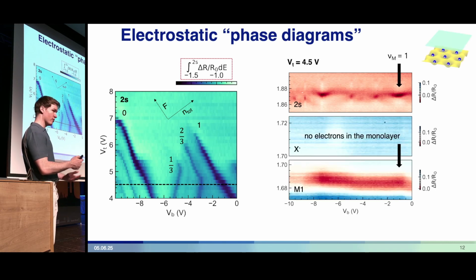If we track the other exciton resonances in the system, we look at the trions in the monolayer — well, they're not there because the monolayer is charge neutral at this low electric field value. And if we look at the M1 Moiré exciton, you see these cusps corresponding to the integer filling.